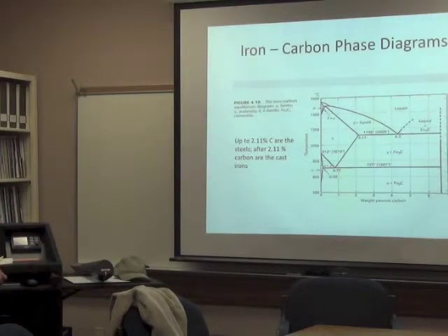And the maximum dissolvability of carbon into the austenite region happens at about 1148 degrees Celsius or 2098 degrees Fahrenheit, and that maximum solubility limit is 2.11%. Right? Then you see here again two-phase regions.